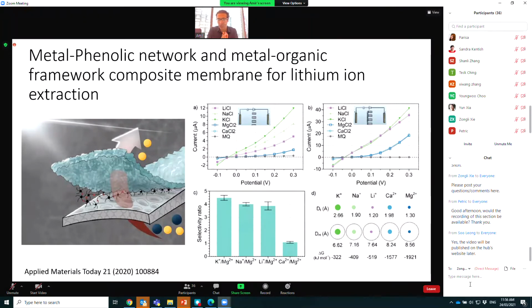In this particular work, we tried to create a thin film MOF on a flexible polymeric membrane. I guess this is an important step towards commercial implementation of MOF thin films for ion separation, because almost 90% of the works put a MOF thin film on a solid-state material. It's very hard to scale that up. But here we've used a bio-inspired approach using polydopamine and a metal phenolic network to create MOF thin film for ion separation.